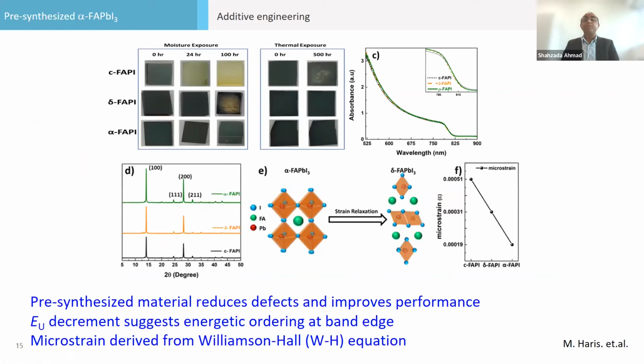Recently, we have been working on alpha FAPI, moving from delta FAPI to alpha FAPI, which means we can make the black phase ourselves. If you look at the conventional formamidinium lead iodide, after some time, 100 hours, it became yellow. Delta FAPI, where you mix, deposit and heat them, also became yellow. But if you make alpha FAPI, it remains black even at 100 hours and 1000 hours of light exposure.